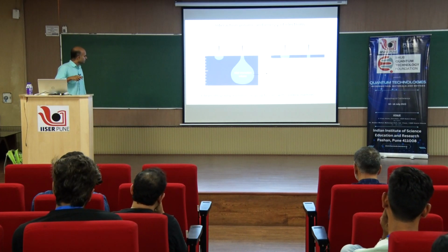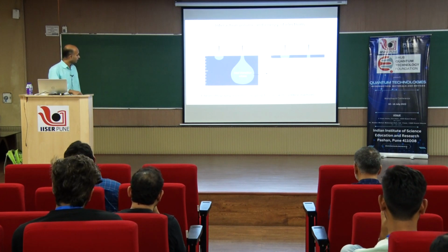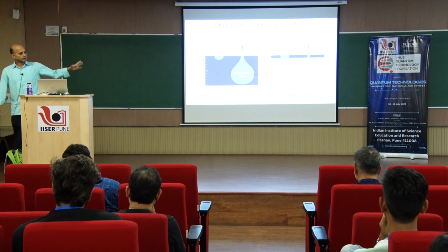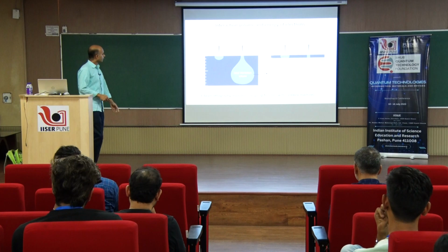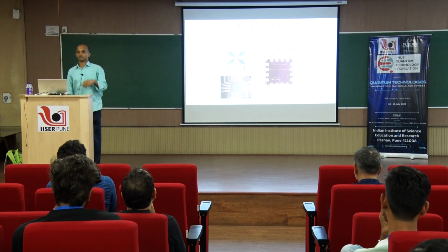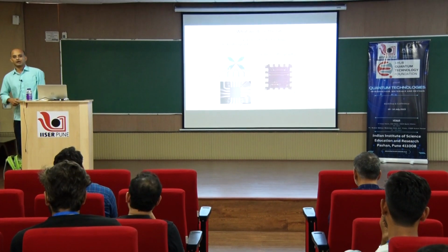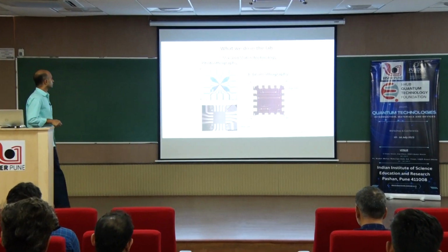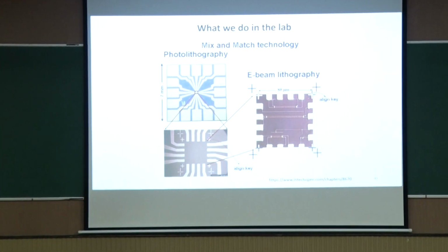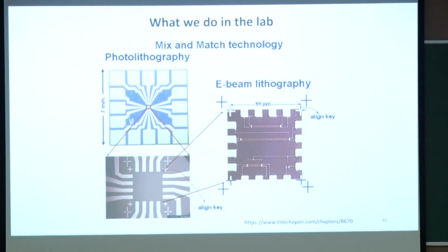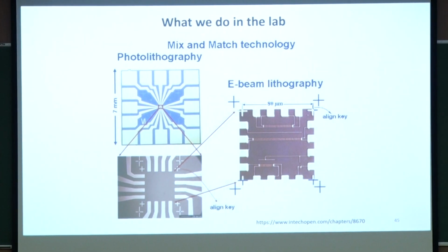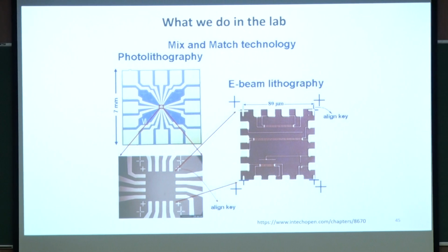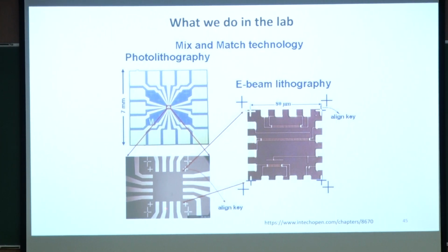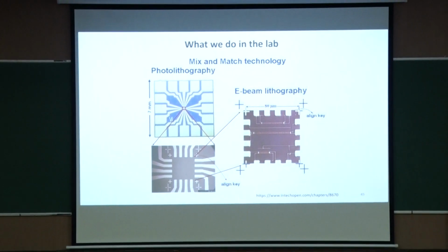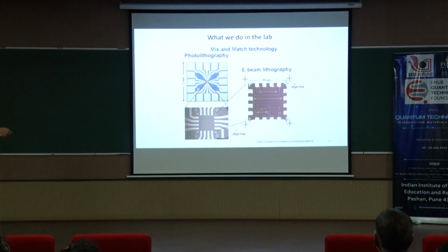These days, the resolution of e-beam lithography can go up to 5 nanometers with a 100 kV machine, not this SEM-based one but the dedicated e-beam lithography, which has a longer column. But in the lab, if you have only e-beam lithography or only optical lithography, you are not in a very good position; you need both. This part you make using photolithography, which you can see is 7 millimeters by 7 millimeters. If you wrote that using e-beam lithography, it would probably take months to make just one pattern, but in photolithography it takes less than 10 seconds to transfer the pattern. Then the intermediate, finer features you make using e-beam lithography. So you need a combination of both optical and e-beam lithography to run your lab successfully and make a device.